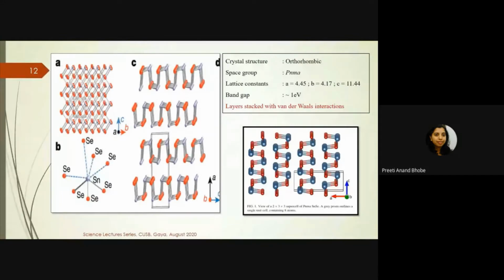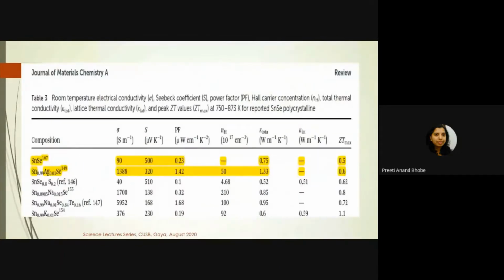And this van der Waals interaction between the layers is what gives rise to its very low thermal conductivity. Okay, because the phonons cannot propagate and the lattice thermal conductivity really reduces. The phonons cannot propagate easily. Heat cannot be conveyed from one part to another in this material, and hence it pulls down the thermal conductivity and increases the ZT. But there is a catch now.